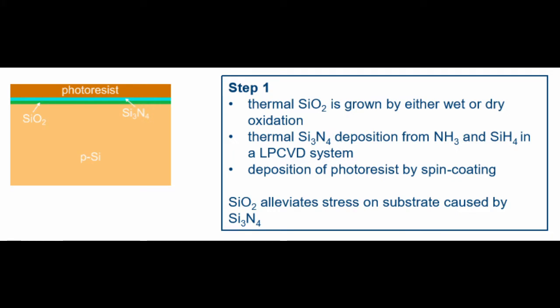First, to form the active region. Thermal oxidation of the silicon occurs, either wet or dry, to produce that thin silicon oxide layer. Notice, however, that before this actually happens, during the manufacturing of silicon there will naturally be a silicon oxide layer. But this is removed due to the fact that it won't be homogeneous, it won't be uniform, and the thickness won't be correct. So it is removed and controlled thermal oxidation is done either wet or dry.